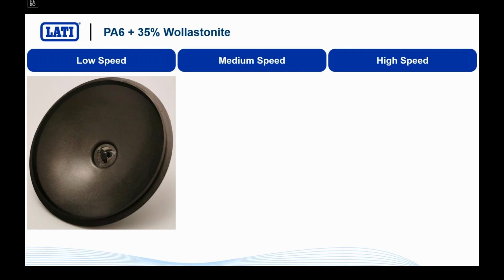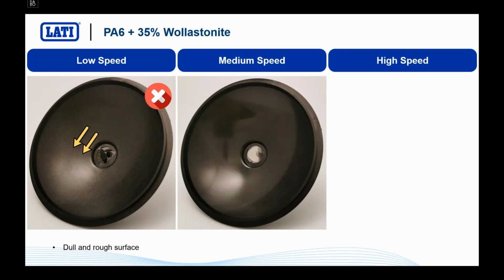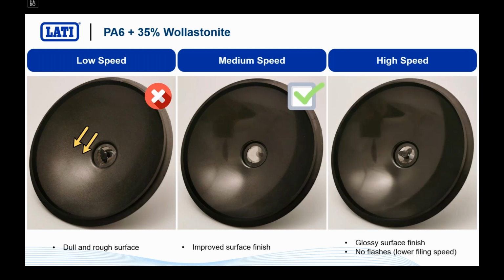We have the same situation here, but with the submarine gate. You have always a very dull and rough surface, which is somehow improved by increasing the speed. And if you increase the speed too much, you do not see that kind of issue that you have seen before. You do not see the flashes, because this specific injection system will somehow reduce the speed of the material filling the cavity. So you somehow reduced also the applied pressure, and you will have an overall good looking part. Also with wollastonite. So the trick here is to increase the speed and to keep under control the speed of the melt into the cavity and applied pressure by using a properly designed injection system.